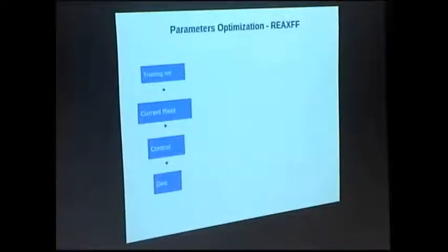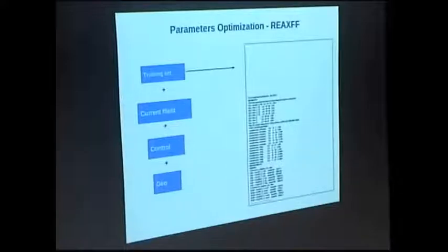And here, one example of how we can do a parameterization, just a really simplified explanation. We define a training set, typically, and here we have the geometry of some molecules. For these molecules, what can we do? Maybe we have a molecule that has an oxygen on one extremity, then we calculate the energy with this oxygen displaced to many positions, and then we map these numbers.